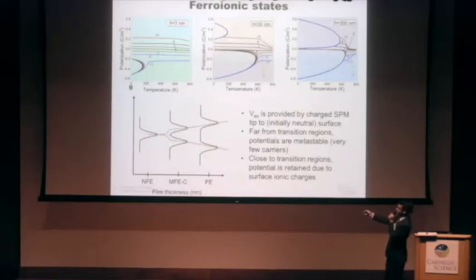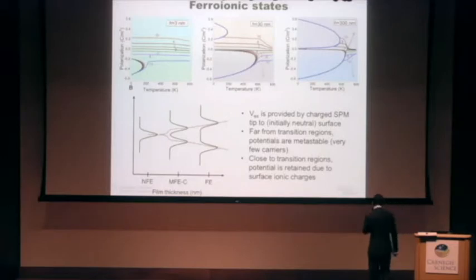I wish the color of the laser were better. It's kind of blending in with this. But in any case, you can see that you can access a range of polarizations by applying potential in this case. Similarly, you can do that for a 30-nanometer film, where now we've kind of recovered the ferroelectricity here. And then for really thick films, it's almost back to the standard bulk ferroelectric type behaviors.